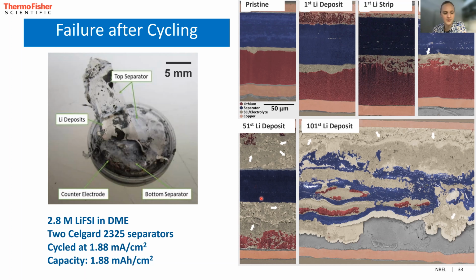And then this 51st deposit really shows that these processes are stochastic. So all of these examples are different batteries, and this battery in this location, it did have a stable separator and didn't have infiltration of the SEI into the separator, but we found that with extended cycling, that was very common. I also point arrows here for the cracks that formed in the SEI as you plate and strip the lithium. And then under failure, you see here at 101st lithium deposition cycles, that there is some lithium metal that deposited within the separator. And so this is just showing a predominant failure mechanism, at least under these conditions.